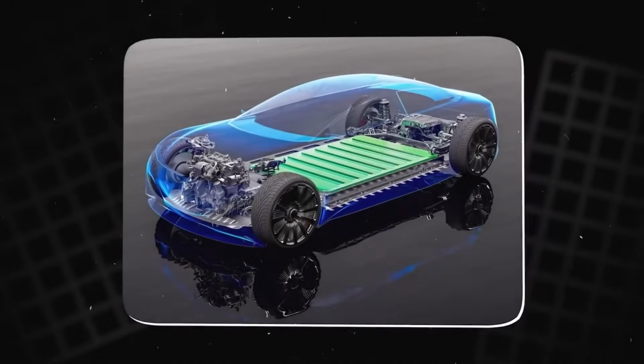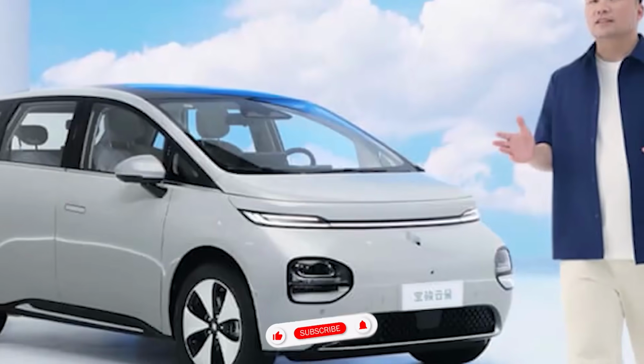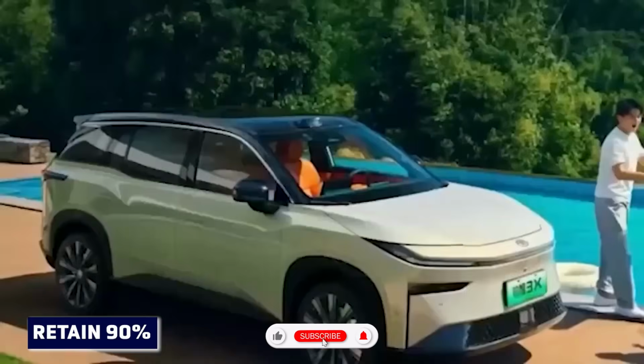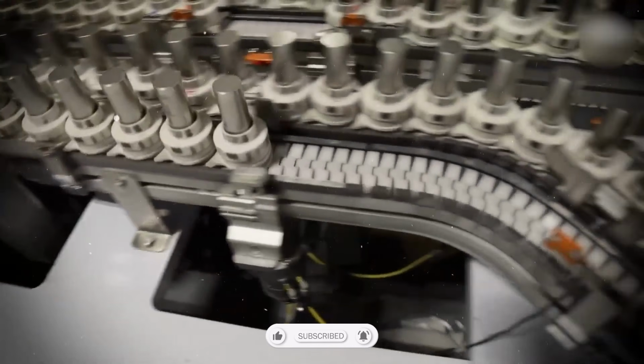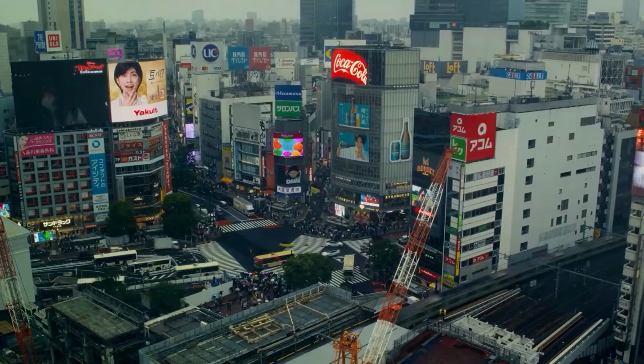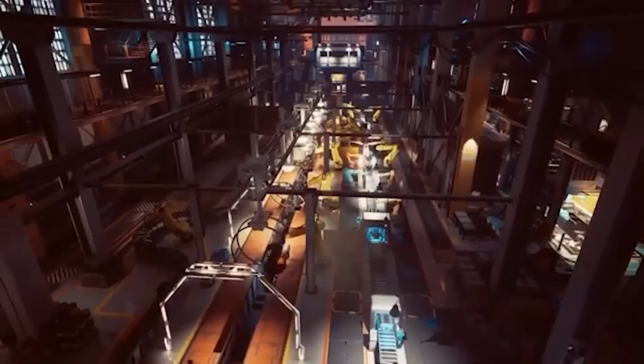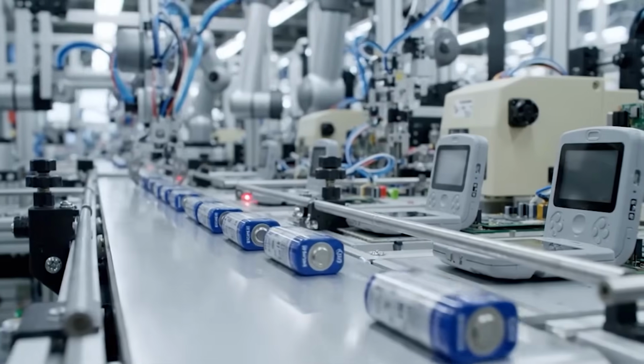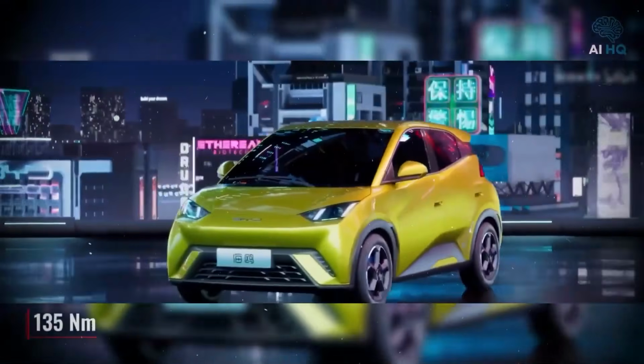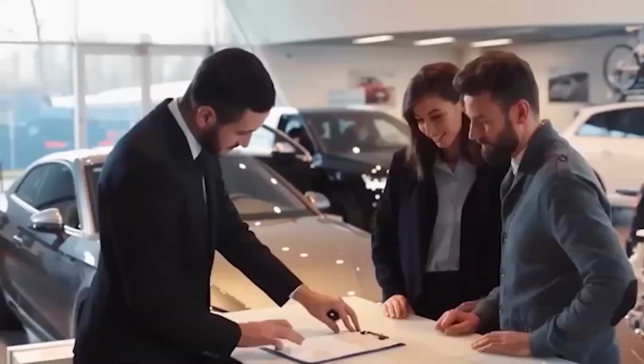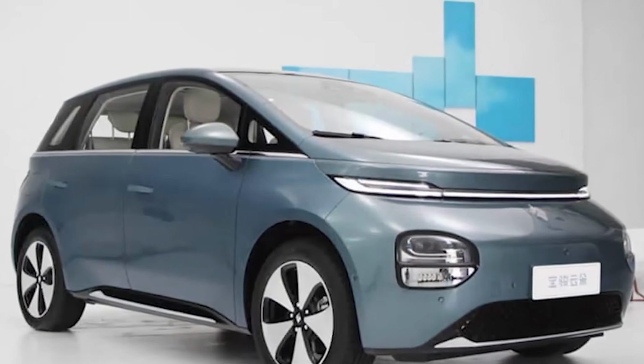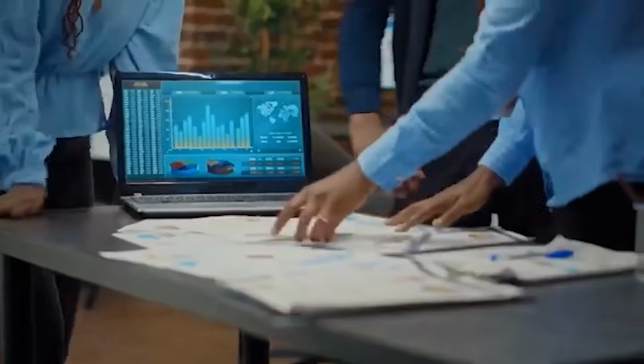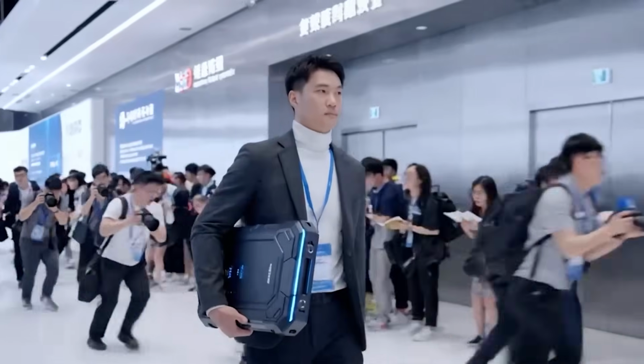China has just put a sodium-ion battery into a production vehicle that can retain 90% of its driving range even at temperatures as low as -40 degrees Celsius. Meanwhile, many lithium-powered electric vehicles begin to lose significant performance long before reaching those conditions, with some struggling even in ordinary winter weather. What's even more remarkable is that this battery contains absolutely no lithium, no cobalt, and no nickel.